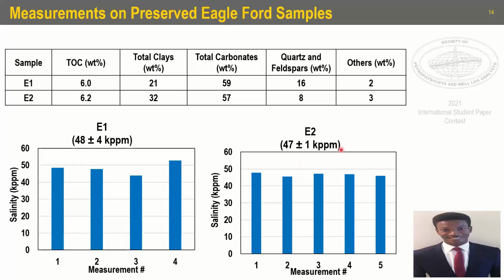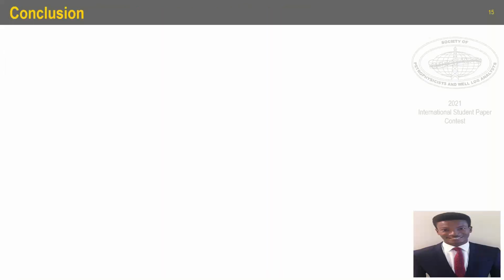Due to the fact that these two samples were gotten from the same formation, but were just separated by 50 feet, we can see pretty much good comparison between the salinity predictions for the two different samples. So this shows a good confidence in our newly developed methodology. This leads to the conclusion of this presentation.